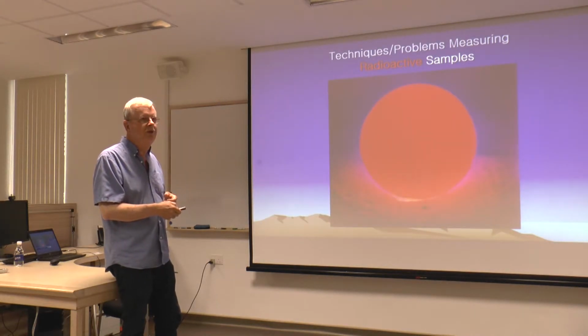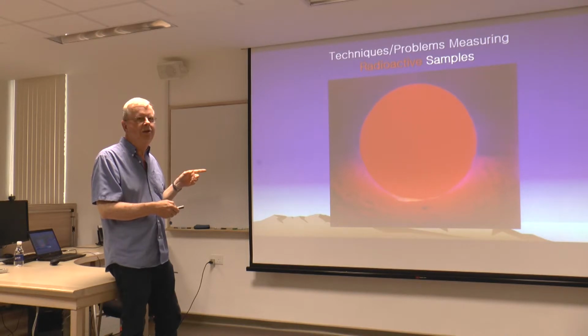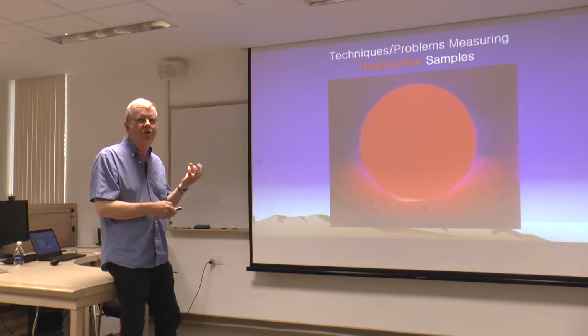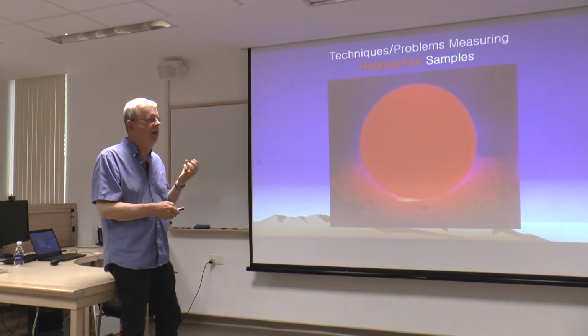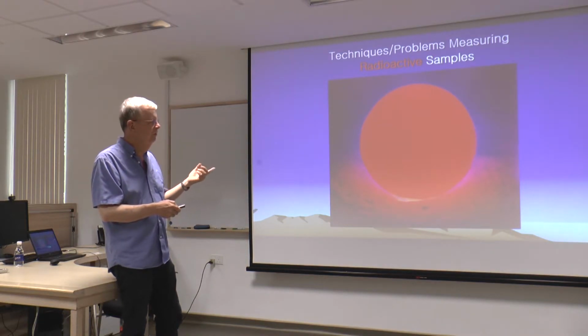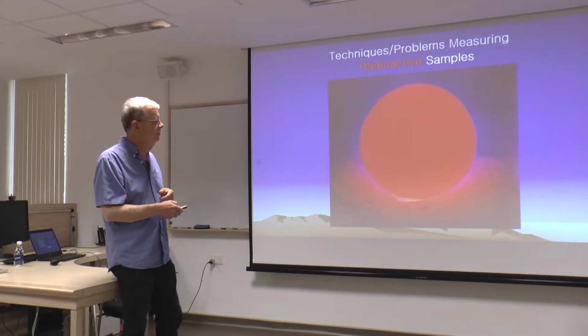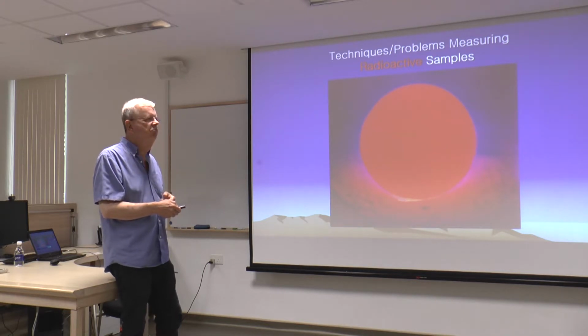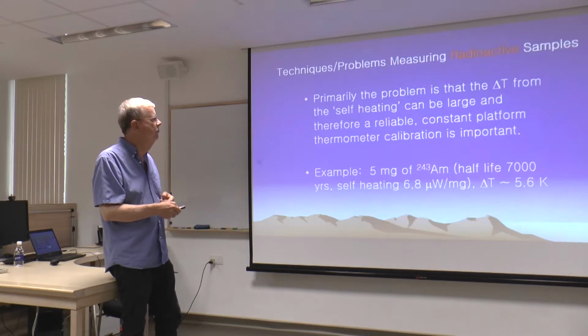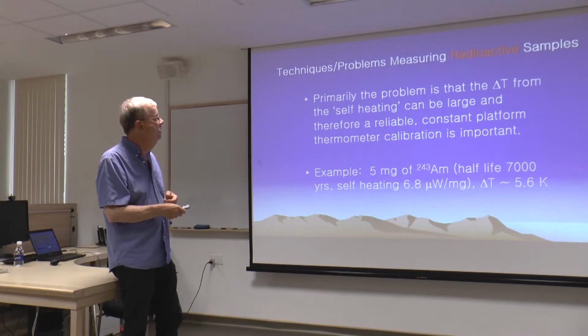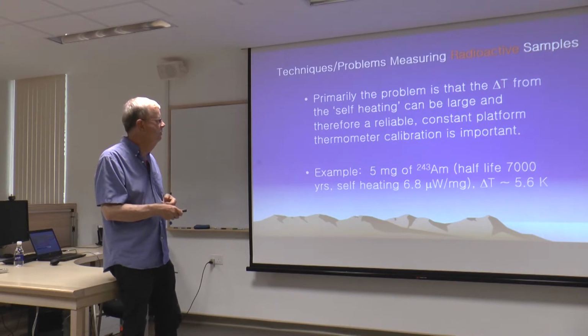This is a ball of plutonium measured with infrared sensitive film, and it's just glowing from its own self-heat because it decays at a sufficiently fast rate, 24,000 years is the half-life of plutonium-239, that it's warm. And so when you measure uranium-containing samples, it's hard to get below 80 millikelvin. It's hard. And it has a difference in temperature between the sample and the surroundings due to the radioactive heat.